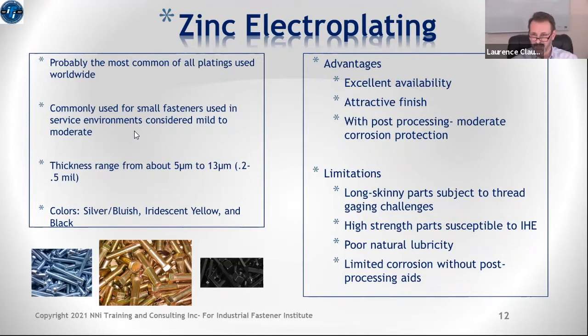It's cost effective, it's attractive, it supplies pretty good corrosion protection when you're using it in mild and moderate environments. Once you start to go to moderate severe and severe service environments, zinc electroplating probably doesn't hold up anymore. But most applications are more in that mild to moderate range, so it's a good fit in those areas. Today, the natural colors are basically silver, yellow, and black. Sometimes the silver is called zinc in blue.